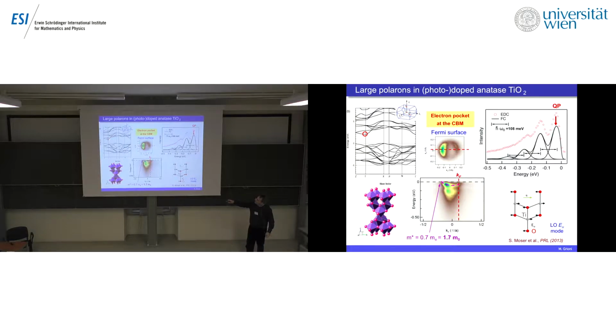So this is the bottom of the conduction band. There is an electron pocket for the doped system. This is the Fermi surface of this electron pocket. And if we cut through this Fermi surface, so we have momentum and energy, this is what we observe. There is the bottom of a parabolic band, but there is something strange. There is a lot of intensity beyond the parabolic band, and also this band is much flatter. The mass is larger than what one calculates with a DFT calculation. In fact, the mass is something like 1.7 times the band mass.